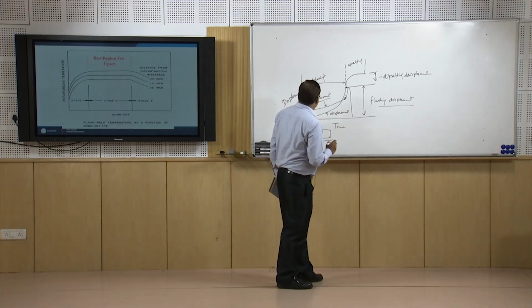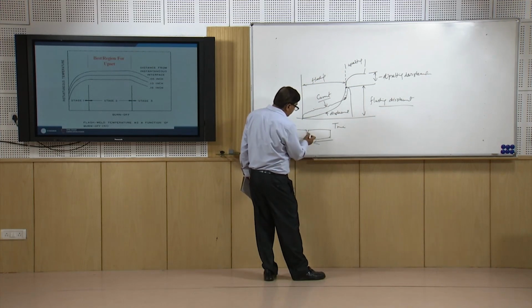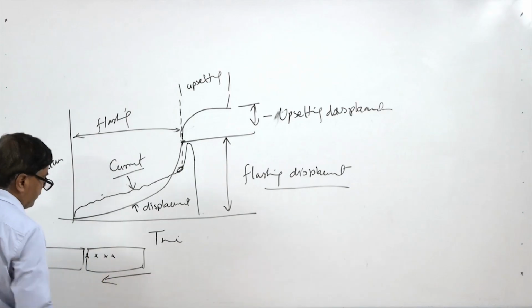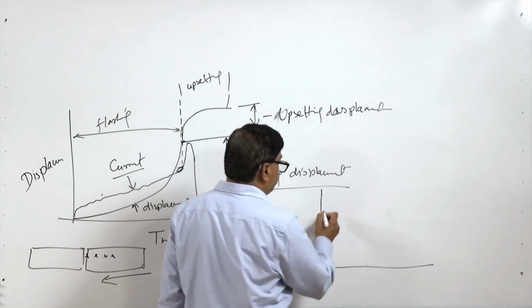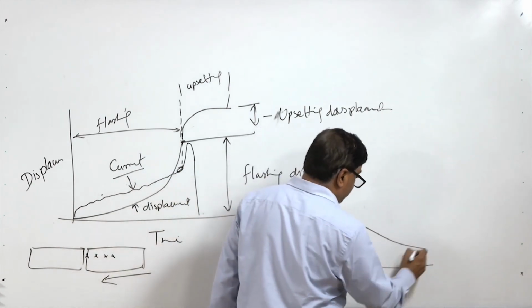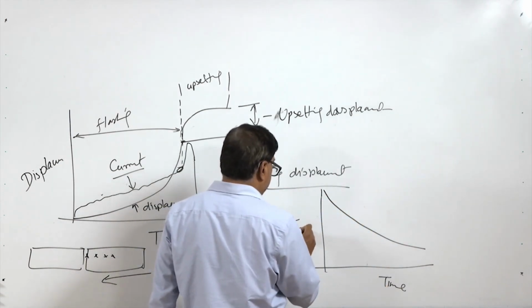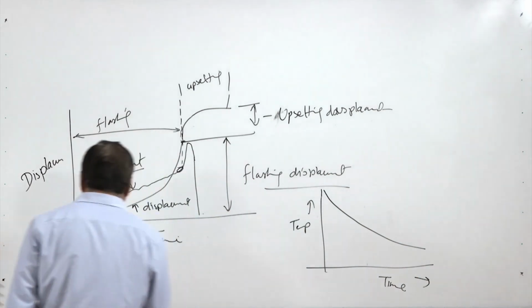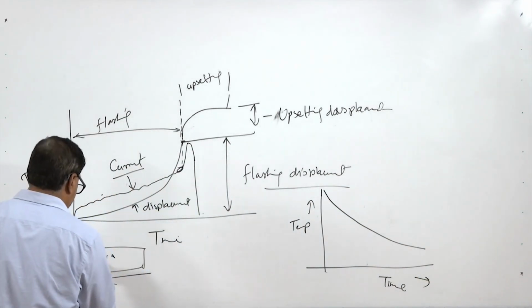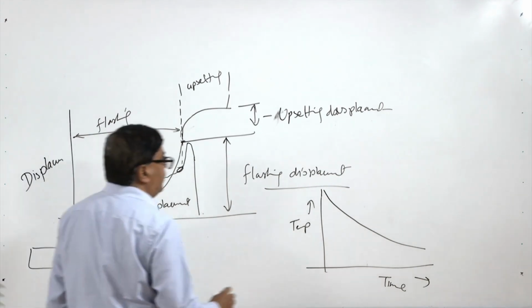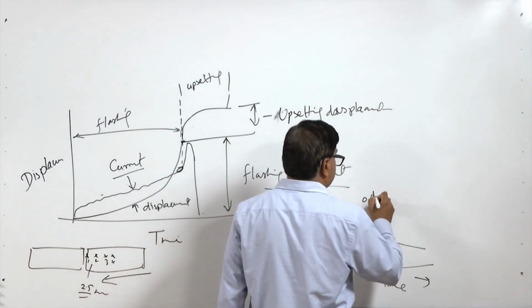And if we see the kind of variations which take place in the temperature at the interface or at increasing distance away from the interface, then typically the weld thermal cycles experienced at the interface show a continuous decrease in temperature as a function of time. Say here is the temperature, and on the other axis the time, and then you will see points 1, 2, 3, 4, say at each interval of 2.5 mm. So, the one at 0 distance, that is at the interface,